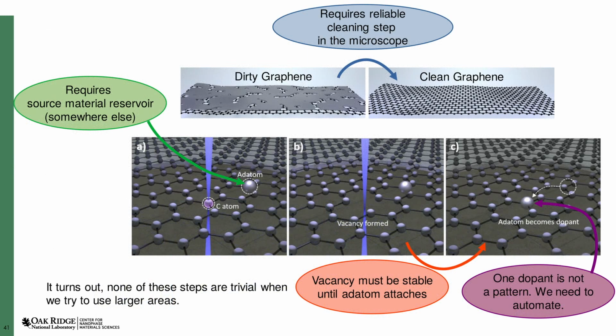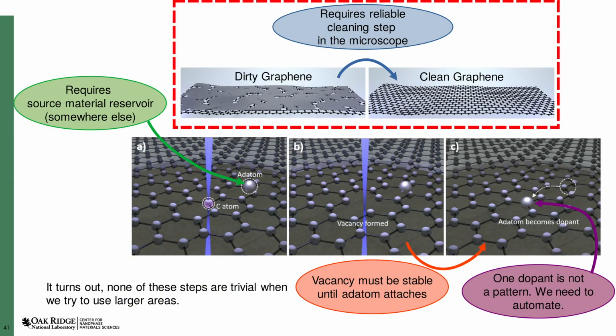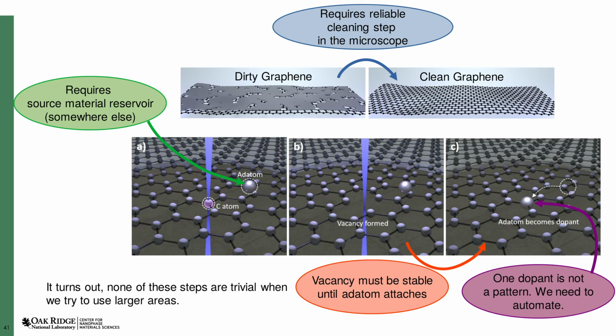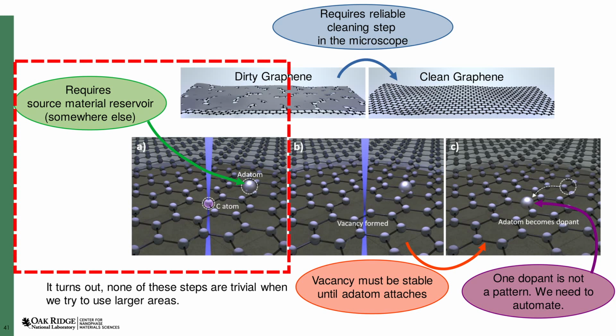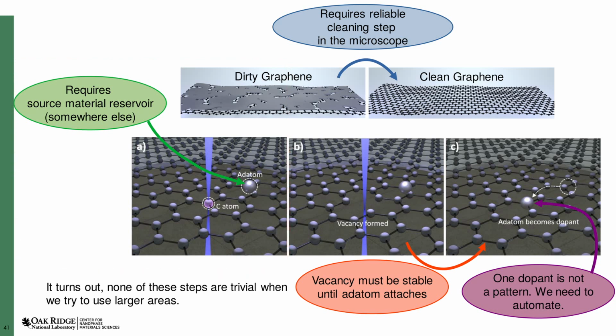These bright nanoparticles are the chromium we evaporated onto the surface, and the rest is representative of the typical contamination found on graphene. So, we have several rather challenging tasks ahead of us. First, we would like some kind of cleaning procedure so that we can obtain and maintain atomically clean graphene in the microscope. Graphene gets dirty just from exposure to the air, so this needs to happen in the microscope vacuum chamber. Second, we don't really want our source material to be adhered to the graphene surface. It's difficult to imagine how one would use this approach to atomic fabrication if you have to deposit a bunch of unwanted material on the surface just to put an atom where you want it.